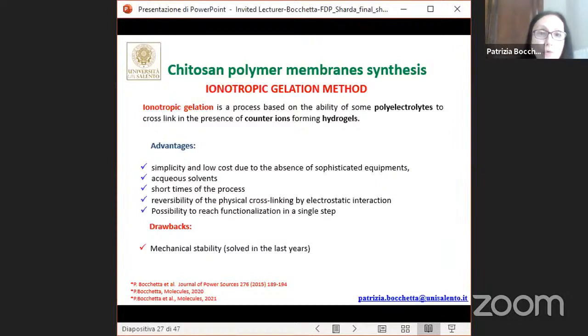and are related to the absence of sophisticated equipment, the use of aqueous solvents, the short times necessary for the process, and the reversibility of the physical cross-linking. Also, there is the possibility of having functionalized membranes directly in a single step. This is possible if we use a cross-linker able to give proton conductivity to the membrane.